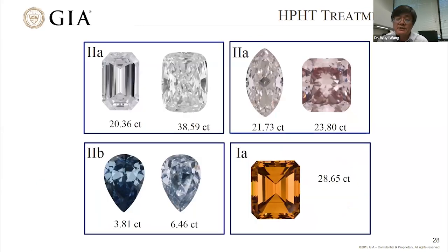So in the laboratory, in GIA, these are just some examples of diamonds after HPHT treatment we identified. These stones were all submitted without any disclosure. As you can see, for type 2A diamond, some of them are up to 38, close to 40 carats. This amazing technology can treat a diamond of this size to decolorize it. Some show beautiful pink, like this 23.8 carat pink diamond. If these 2B diamonds were naturally colored in the auction house, I would believe they would go higher than $1 million per carat for a diamond with this type of color.